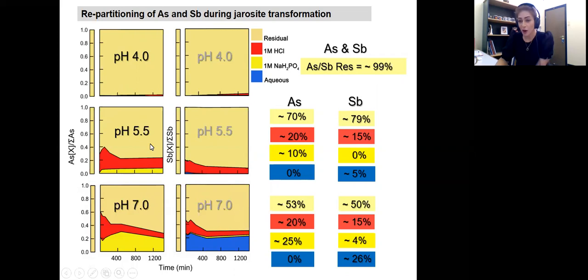But with pH 5.5, what we observed was the repartitioning of arsenic, which was initially locked inside the structure of jarosite, to the surface. About 10% of arsenic repartitioned to the surface. And then about 70% of it remained in the residual fraction, which was good news, because if they are locked inside the structure and in the residual fraction, it means that even if we have future transformation in our mineral for any reason, or even just recrystallization, the risk of release of these trace metals and metalloids to the environment is not that high, and it actually is very low.